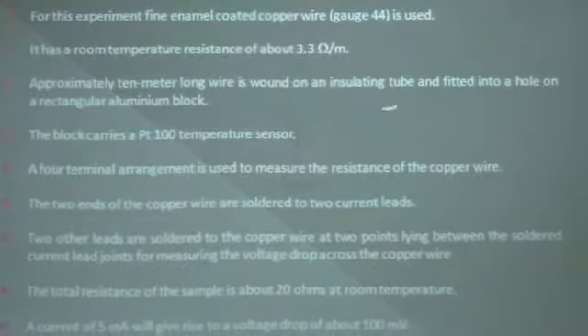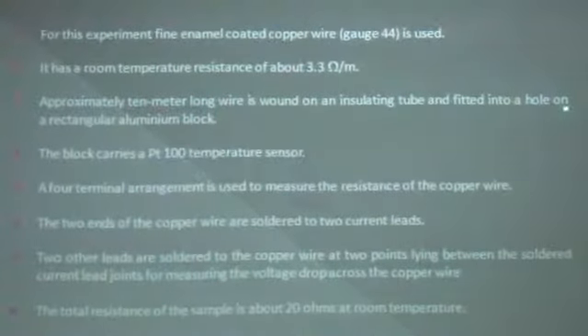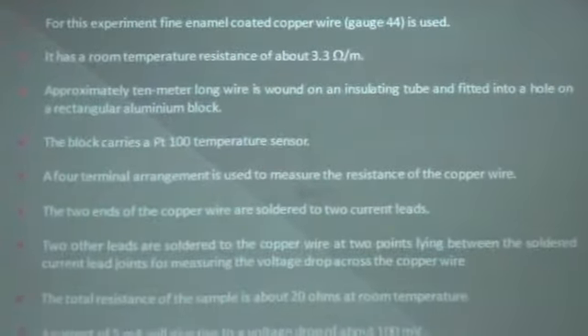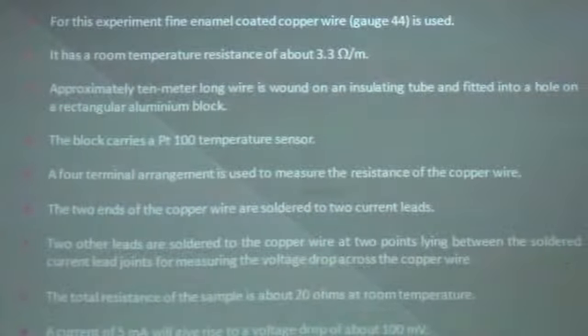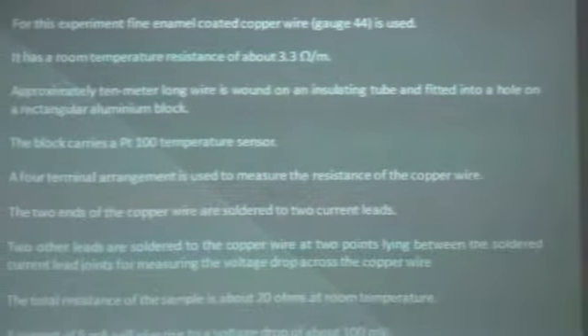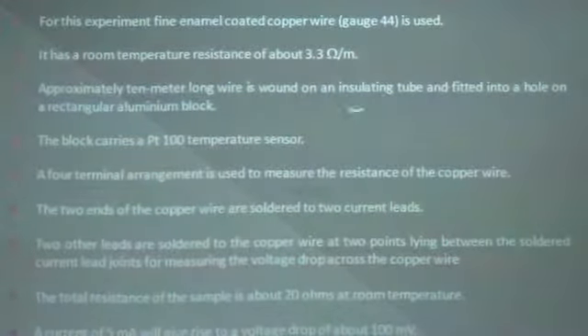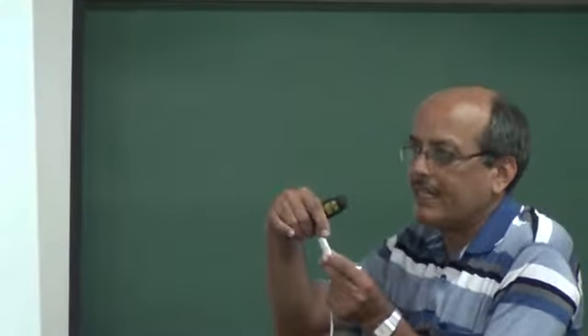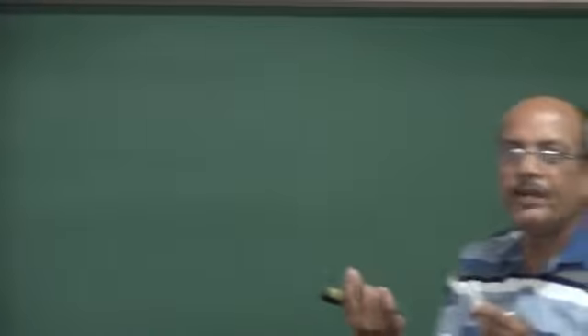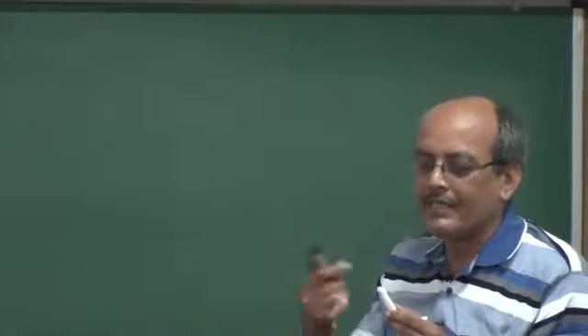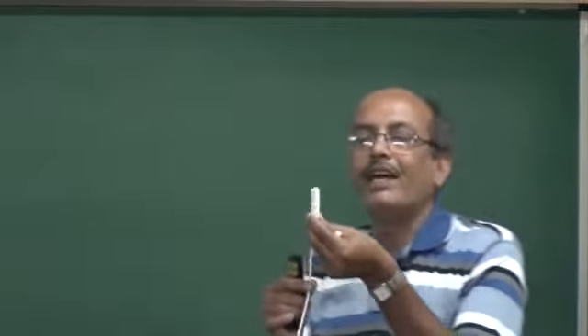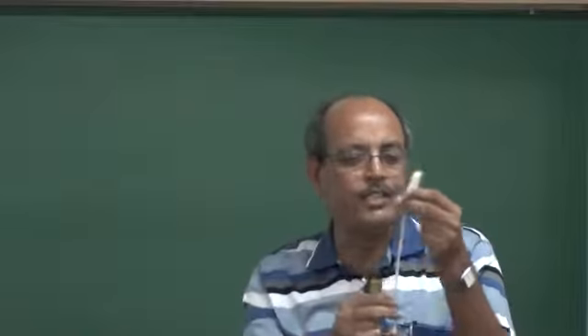It is wrapped onto an insulating tube and fitted into a hole on a rectangular aluminum block. This is a rectangular aluminum block. It is common in all the experiments. Okay, so for this particular experiment, an insulating stand has been taken and the copper wire, 10 meter wire, has been inserted here. You can see 4 terminals coming out, 2 for the voltage measurement and 2 for the current measurement. So it has been inserted, and the white thing, this is a Teflon tape just to insulate everything.